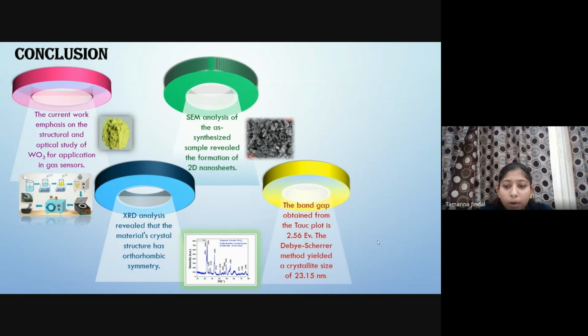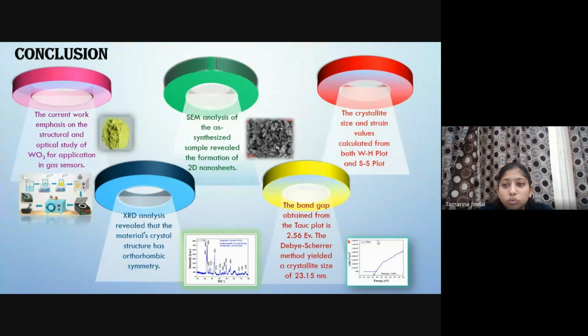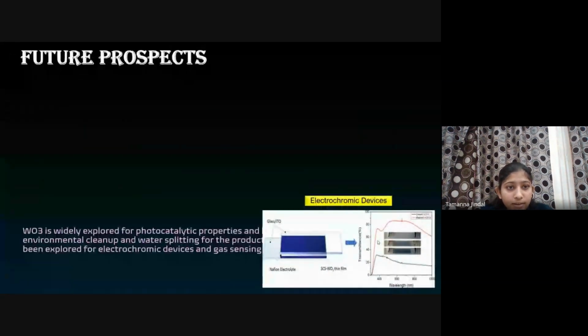And the band gap obtained from the Tauc plot is 2.56 electron volt, and using the Debye equation the crystallite size is about 23.15 nanometer. And then the crystallite size and strain were also calculated by using the WH and size-strain plot, as I have already mentioned. Now the future prospects.